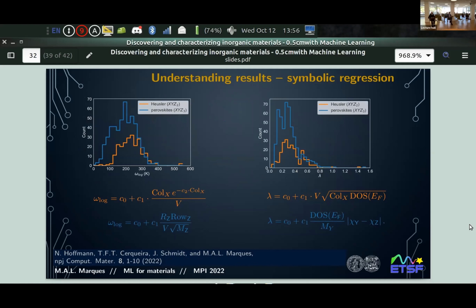I just wanted to show, because people usually say, and with some reason, that machine learning doesn't teach us anything, right? It's just numbers, a black box. And I want to show you that actually one can use it to understand things. This is, again, superconductivity. We did essentially all the Heusler and all the anti-perovskite compounds. And there are around 1,000 of each that are stable, close to stable, in our calculations. And this is omega log, the histogram, and this is the electron-phonon coupling constant. And there are some models in machine learning where the model is a formula. So you basically give it data, and it tells you what is the formula that best fits this data.